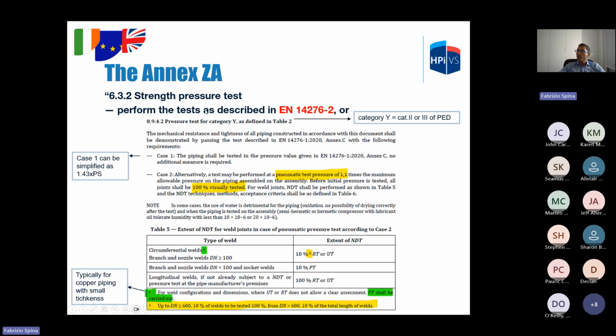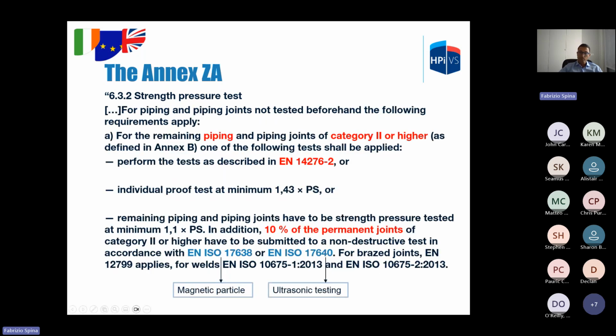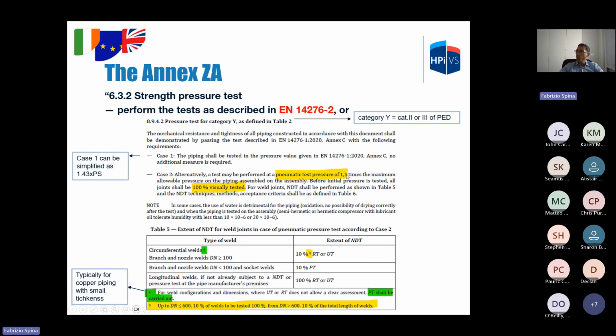In this slide, we can check option 1. This is a snapshot of EN 14276 part 2. Category Y piping is the same as category 2 or 3 of PED. And it foresees two cases. Case 1, which is the same as before, a pressure test at 1.43 PS. And case 2, which is similar to the third point in the previous slide, a pneumatic test at 1.1 PS, 100% visual inspection, and NDT.